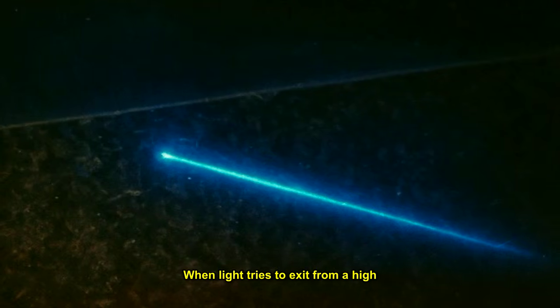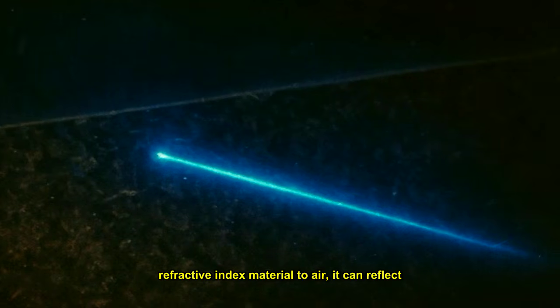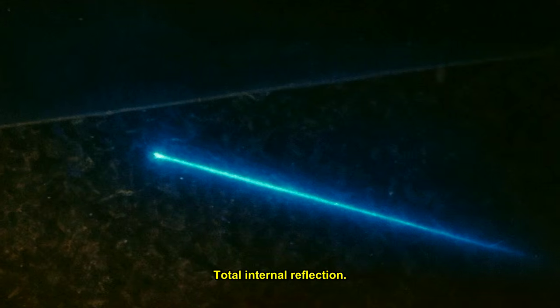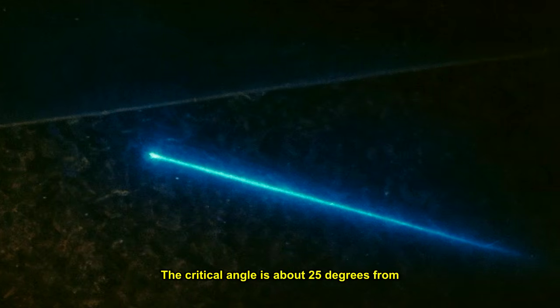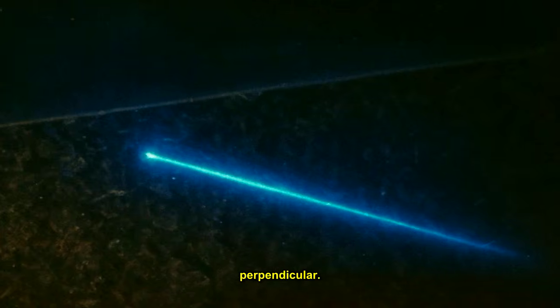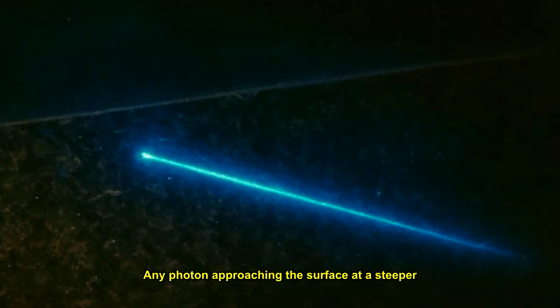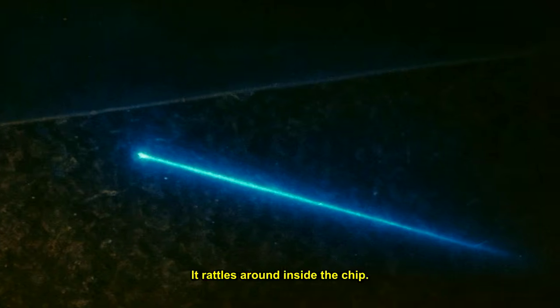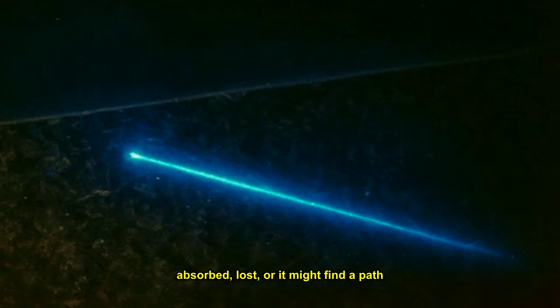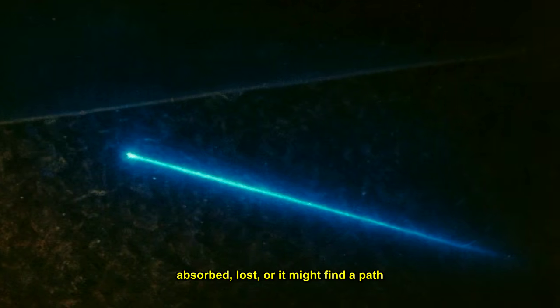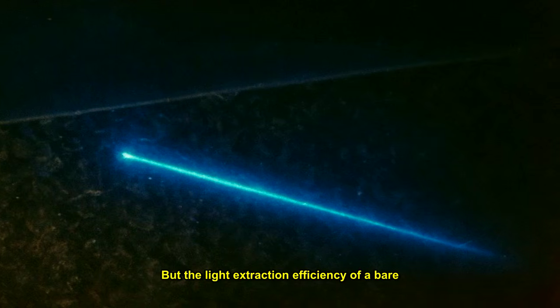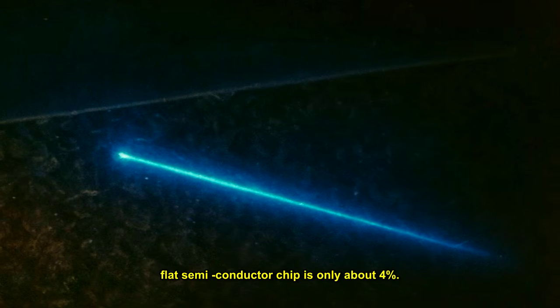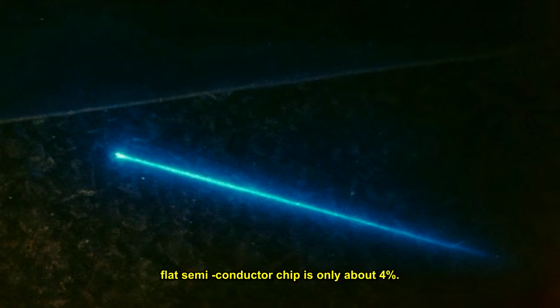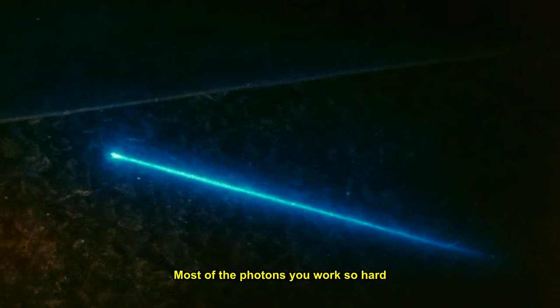When light tries to exit from a high refractive index material to air, it can reflect back. Total internal reflection. The critical angle is about 25 degrees from perpendicular. Any photon approaching the surface at a steeper angle bounces back. It rattles around inside the chip. Eventually, it might hit an impurity and get absorbed, lost, or it might find a path out. But the light extraction efficiency of a bare flat semiconductor chip is only about 4%. This is terrible. Most of the photons you work so hard to create never escape.